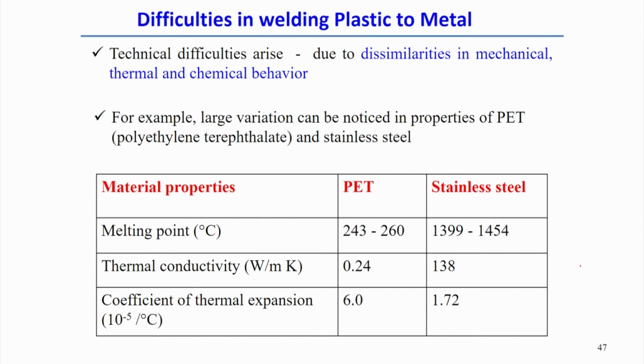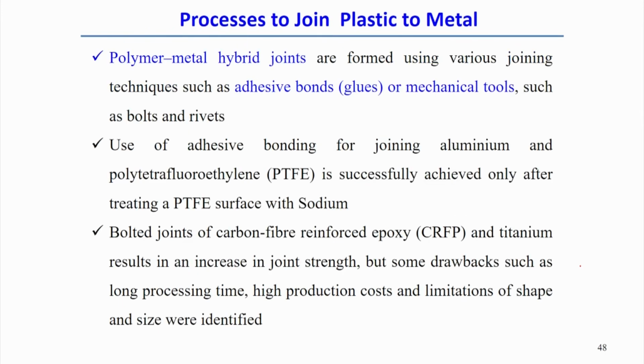So there is a huge difference in the properties, and therefore it is very difficult to join these two materials, but several methodologies have been developed for joining plastic to metals. One is polymer metal hybrid joints, formed using various joining techniques. Simply use adhesive bonds, simply using some glue or some mechanical tools, which is the most convenient way to join these two components. Use of adhesive bonding for joining aluminum and PTFE was successfully achieved, but only after very good surface treatment with sodium. Therefore, surface preparation is one extra requirement in this case.